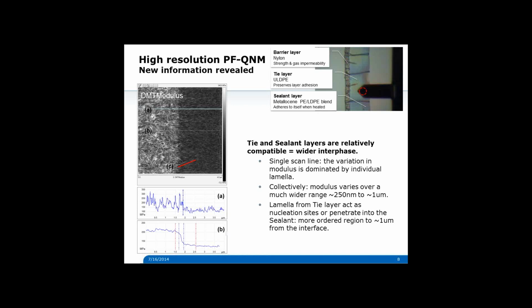And you can also see that some of the lamella actually cross over from the tie layer into the sealant layer, and they can go for up to about a micron into the sealant layer. Sorry. So that's one of the reasons that this works so well, is that basically the tie layer is very well connected to the sealant layer.